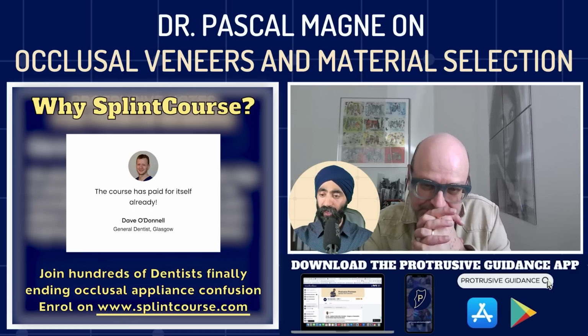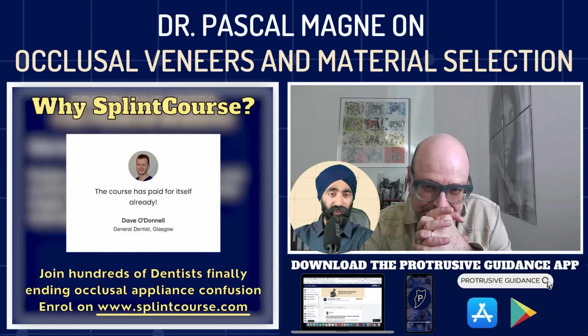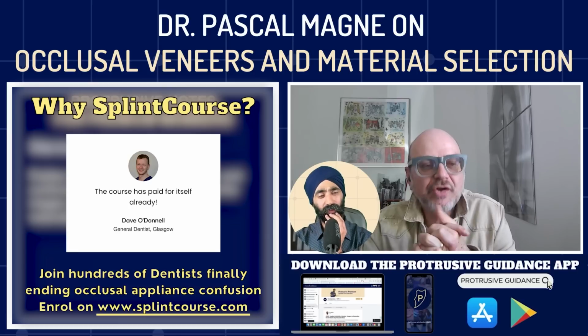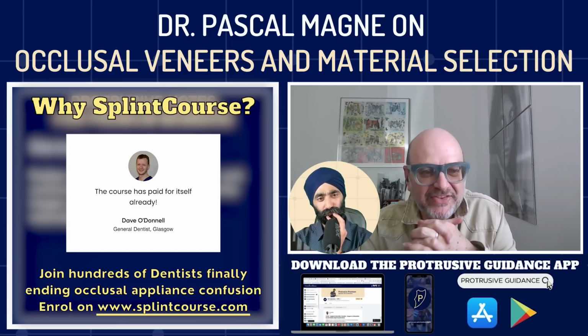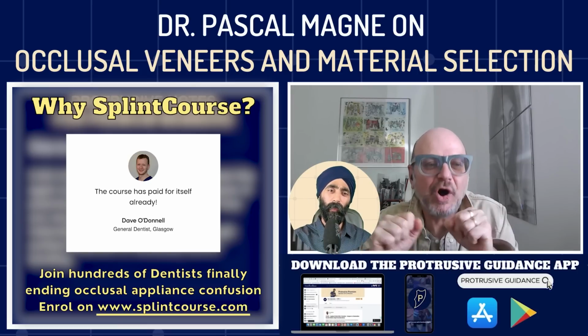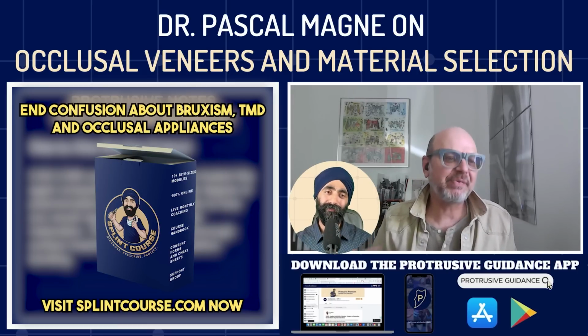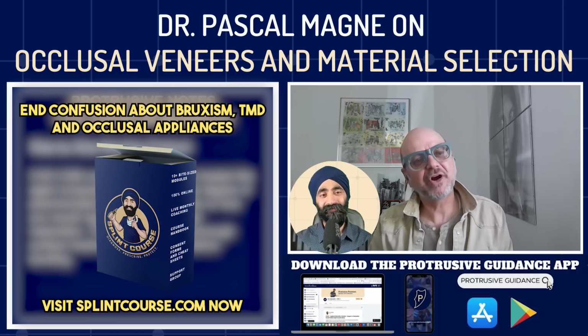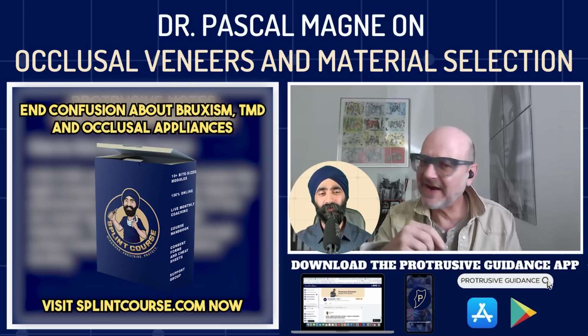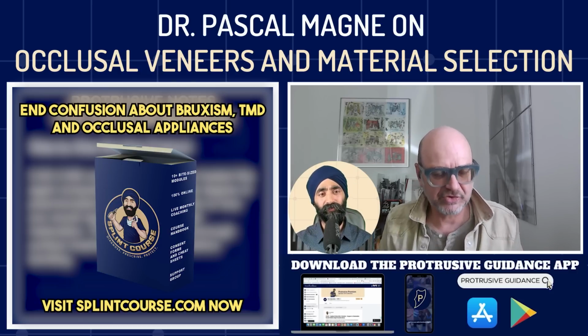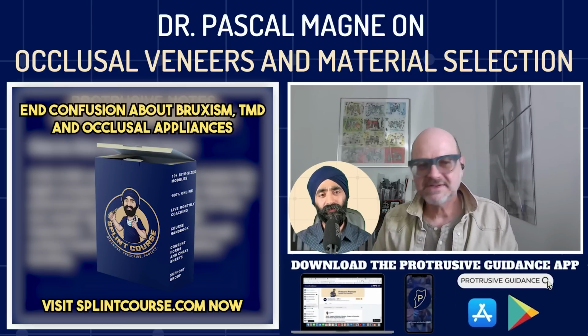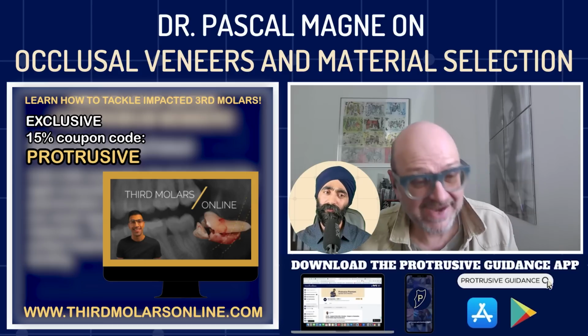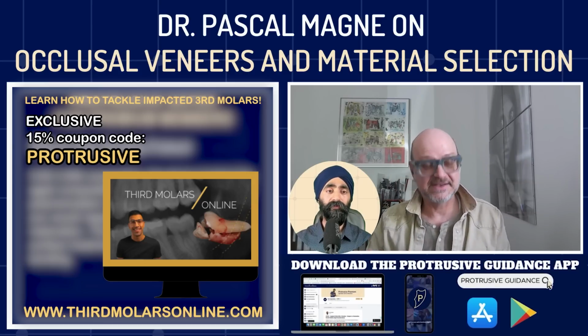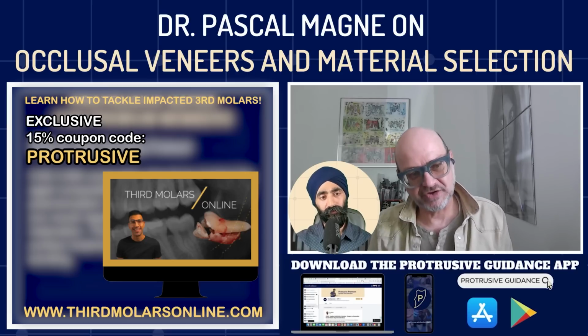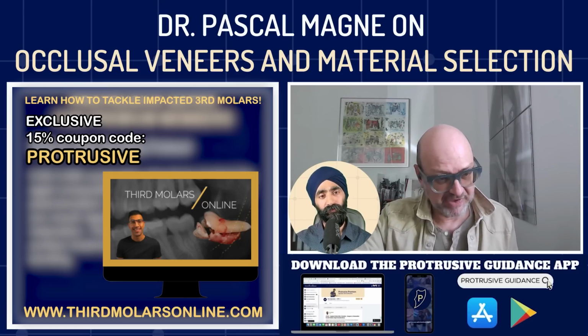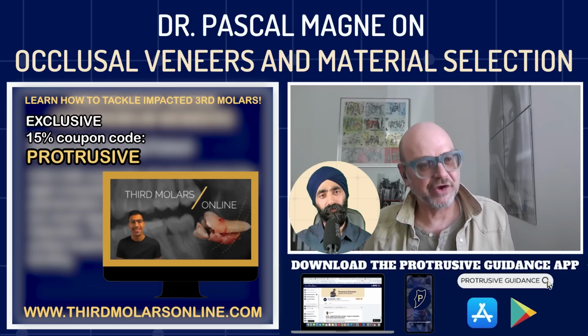And so rubber dam and just, are you going to air abrade the intaglio of your CAD-CAM composite? Yes, so CAD-CAM composites, they need to be treated like an aged composite. Basically, when you repair a composite that you did recently, you just air abrade, wet with adhesive resin, you're good. If it's a composite that's been in the mouth for 6 months, a year, then you have to air abrade with CoJet, silanate, and add adhesive resin. So those CAD-CAM materials, because they are highly polymerized, you have to treat them like a repair.